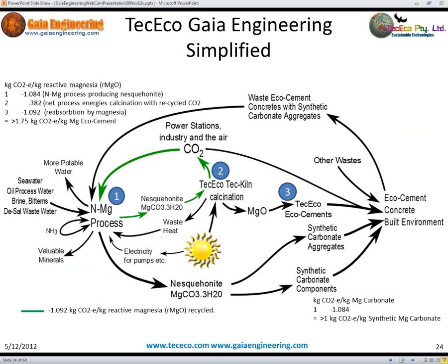Stage 1, the NMG process. Stage 2, the TecEco kiln, calcination. Stage 3, our eco-cements bonding together synthetic carbonate aggregates to create carbonate concrete. In stage 1, the production of nesquihonite, the sequestration is 1.084 kilograms of CO2 per kilogram of nesquihonite produced. The kiln has net emissions of 0.382 kilograms of CO2 per kilogram of magnesium oxide produced, and the reabsorption of CO2 by our cements, the stoichiometric amount of sequestration, occurs at 1.092 kilograms of CO2 per kilogram of magnesium oxide. In total, that's about 1.75 kilograms of CO2e per kilogram of magnesium eco-cement.